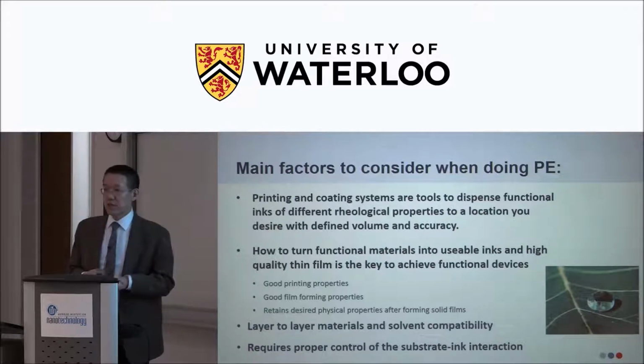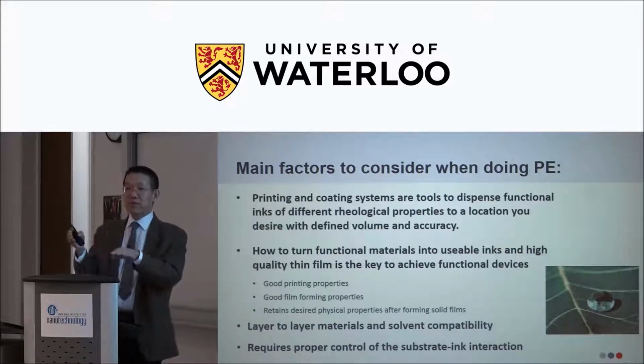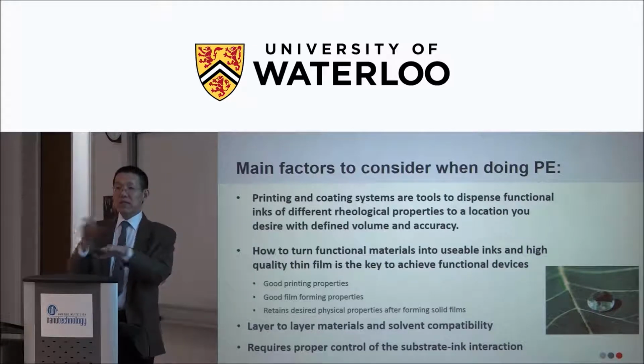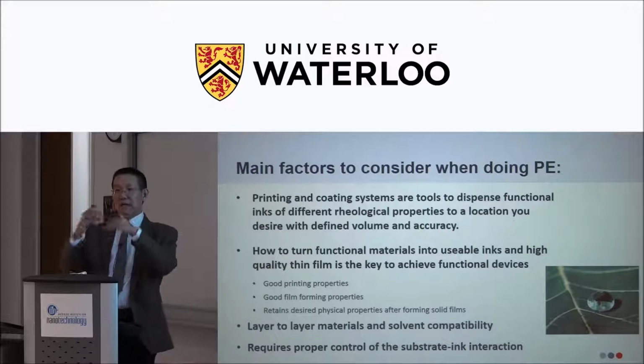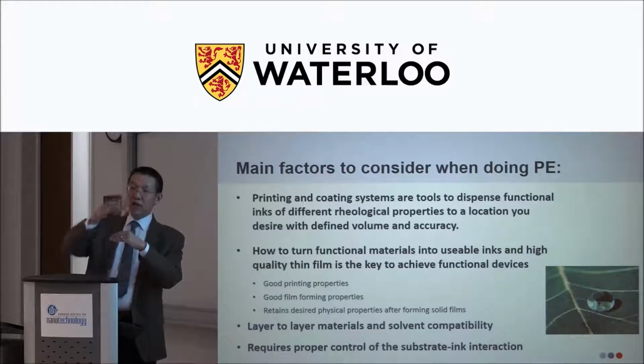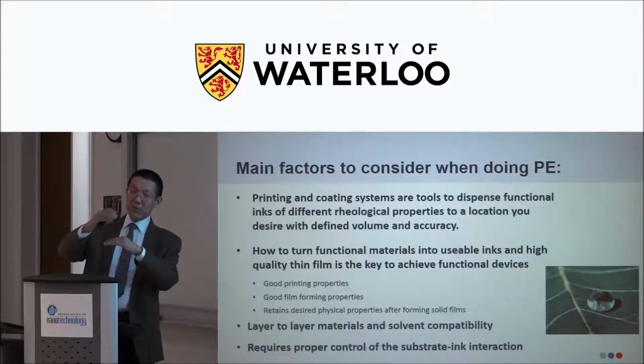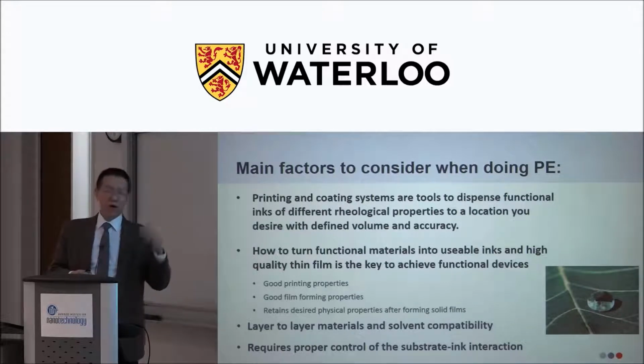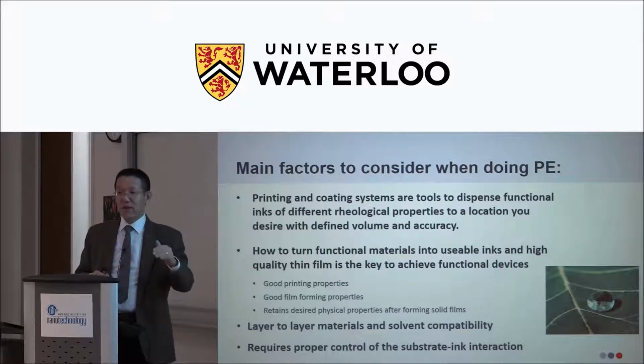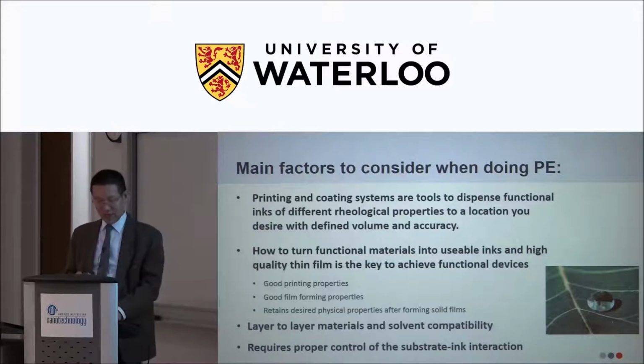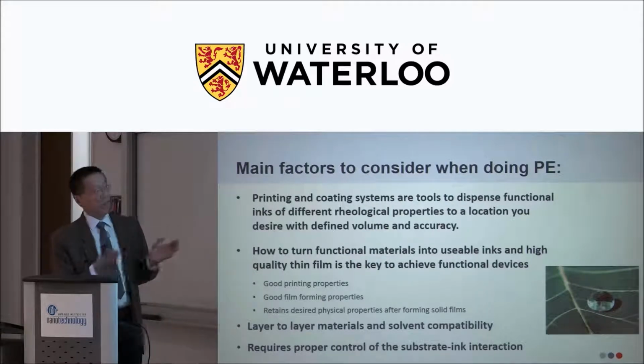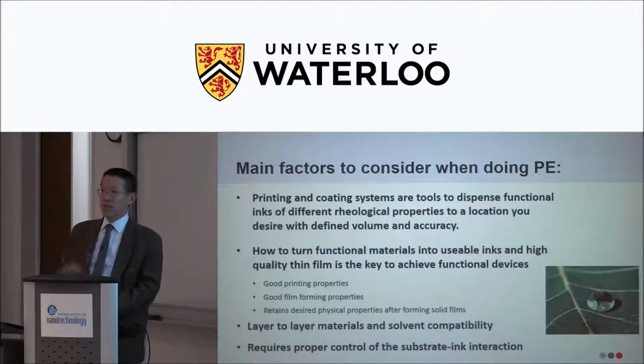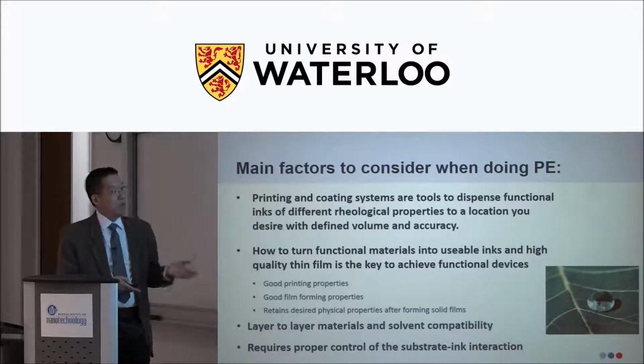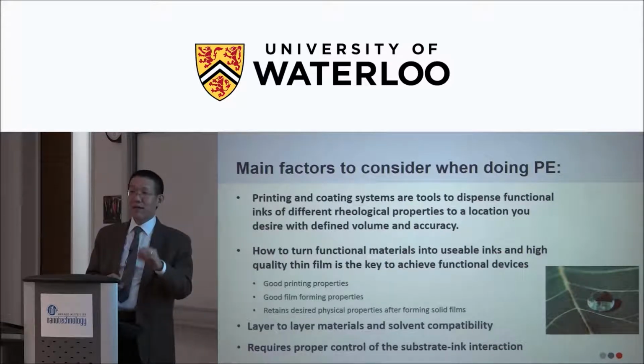Because in the graphics industry, when you print, you rarely care about the layer-to-layer interaction. You care about lateral interaction because when you print color prints, you put the three colors side by side, right? Occasionally, when they make multi-layer printing, it is to make the top layer look the most beautiful. That's their purpose. They don't care too much about the interface between each layer. But when you make organic devices or semiconductor devices, the interface is a very important property in your device fabrication process. So you need to consider all these control factors when you design a fabrication process. So the most important process, of course, is the interaction of that ink with your substrate.